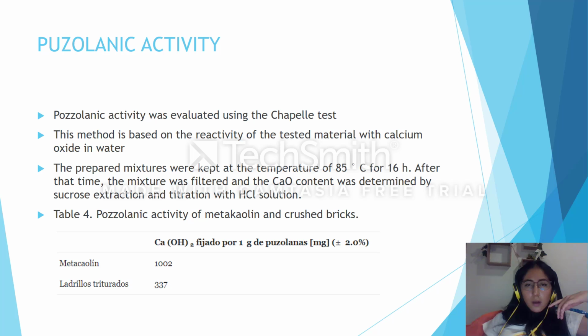This topic is very important because it explains how the pozzolanic activity was evaluated, using the Chapelle test. This method is based on the reactivity of the test material with calcium oxide in water. The prepared mixtures were kept at a temperature of 85 degrees centigrade for 16 hours. After that time, the mixture was filtered and the CaO content was determined by sucrose extraction and titration with hydrochloric acid solution. In Table 4, we can see the pozzolanic activity of metakaolin and crushed bricks.